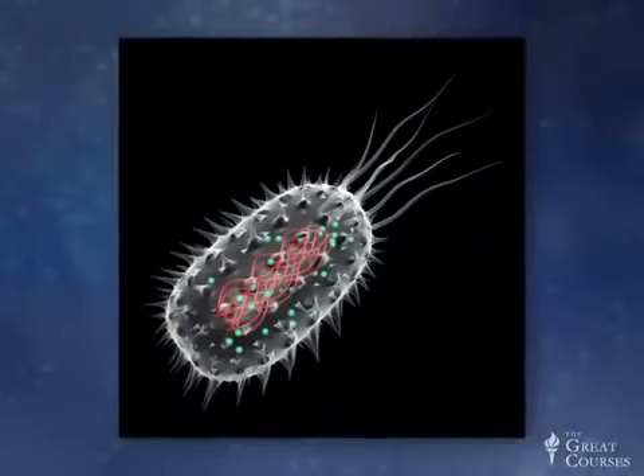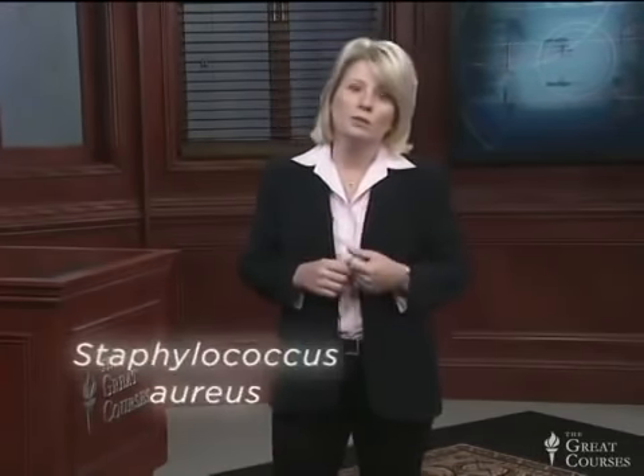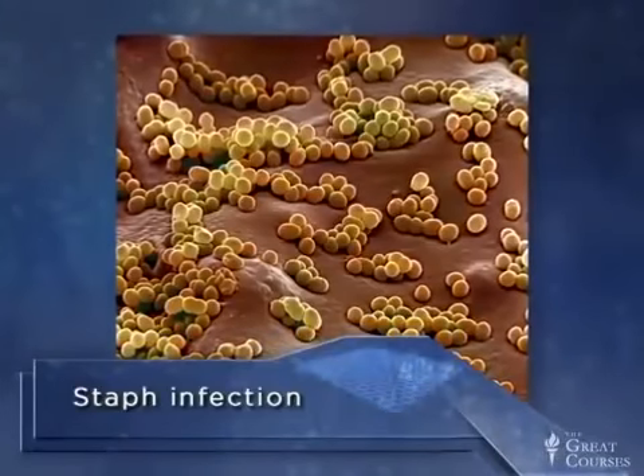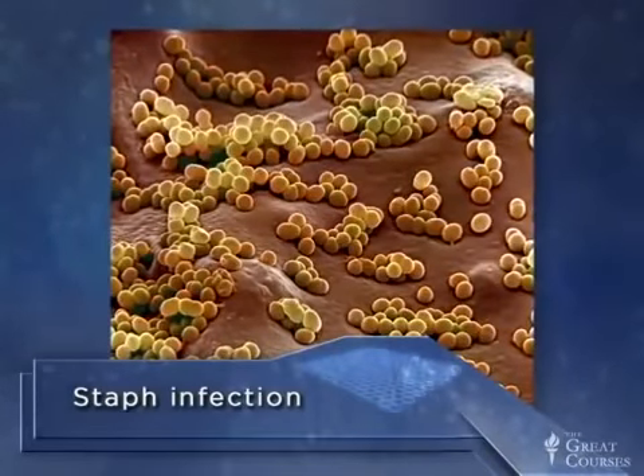And it turns out that we can use the same approach to selectively kill bacterial cells. We can also get antibodies that are specific for certain types of bacteria and basically play the same game. So in a study done at the University of Arkansas, a group in the microbiology department there generated gold nanoparticles that carried an antibody specific to the bacterium Staphylococcus aureus. You've probably heard of the infections caused by this bug. They're typically referred to as staph infections. And they can be quite serious, even or especially if the bacteria ends up in the blood.